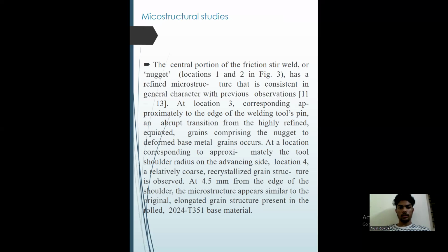This is consistent in general character with previous observation at location 3, corresponding approximately to the edge of the welding tool pin. An abrupt transition from the highly refined equiaxed grains comprising the nugget to deformed base metal grains occurs at a location corresponding to approximately the tool shoulder radius on the advancing side. At the location, a relatively coarse recrystallized grain structure is observed at 4.5 mm from the edge of the shoulder. The microstructure appears similar to the original elongated grain structure present in the rolled 2024-T351 base material.